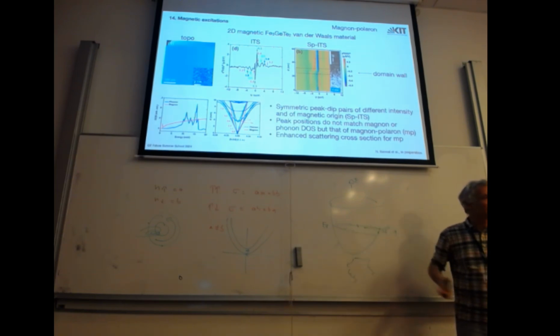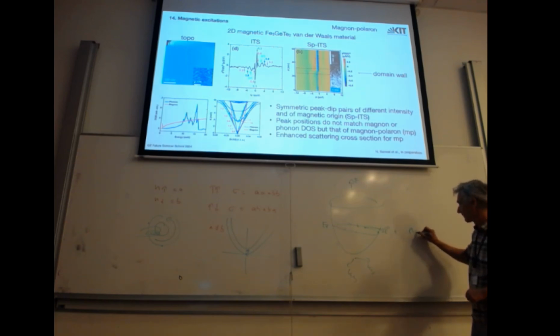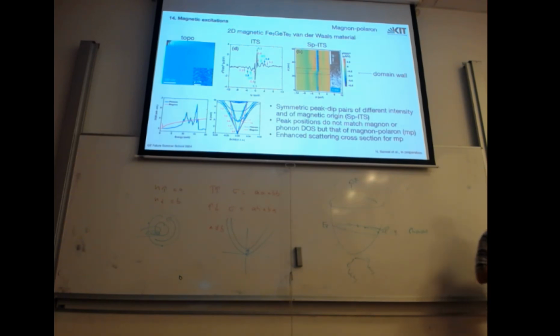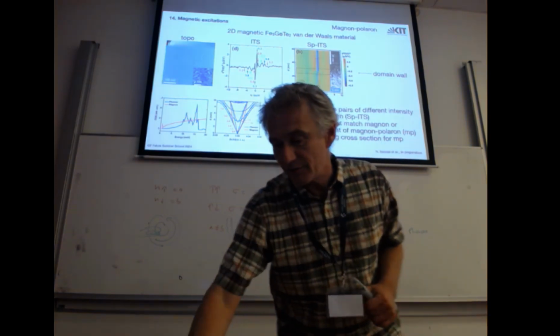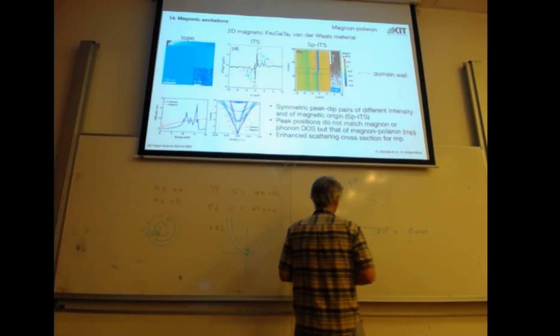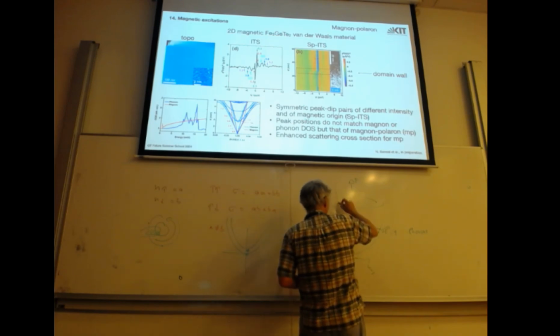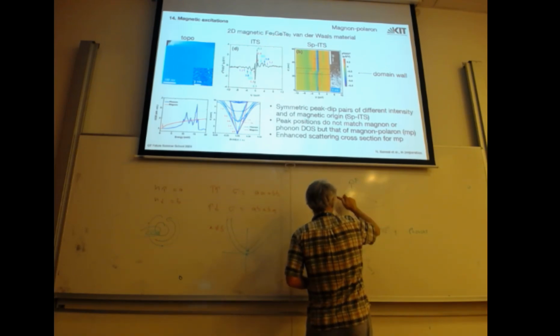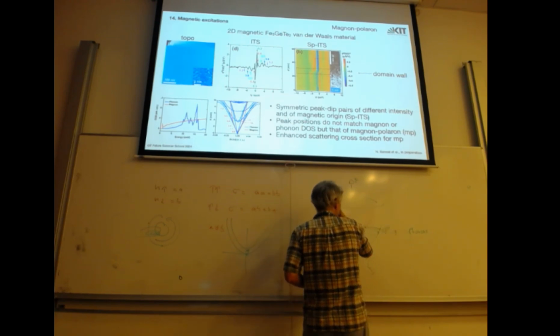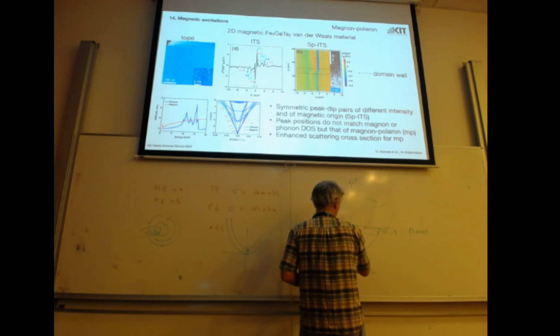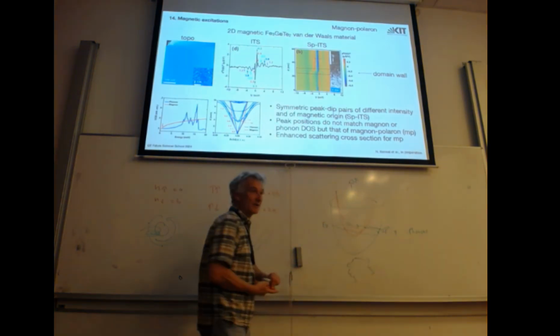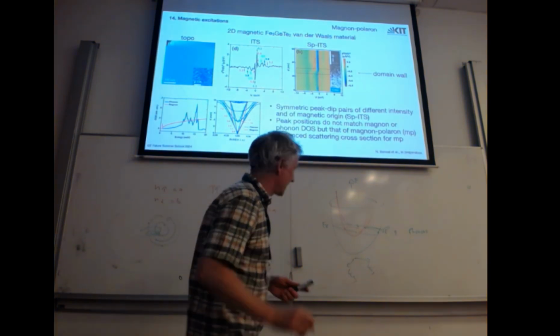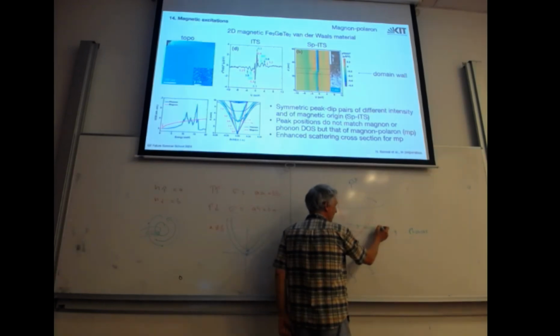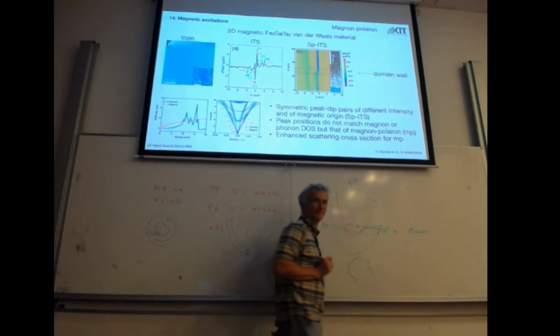If I stay on the same band, these are phonons. Phonons will show up like that. Phonons, electron-phonon coupling is small like that. It's not a big scattering matrix element. Matrix is small. If you have a ferromagnet, you have 2 bands. So for spin flip scattering, I have to go with my electron from one band to another band.